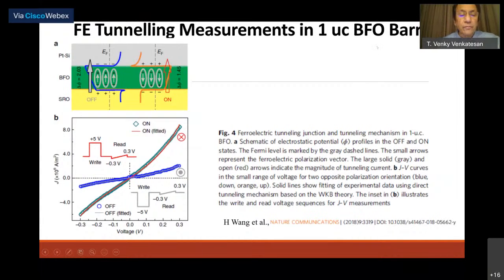We've also demonstrated with bismuth ferrite (BFO), a 1 unit cell ferroelectric layer, and here is an on-off ratio, which is very finite, telling you that a 1 unit cell ferroelectric behaves like a ferroelectric. Prior to these data, there was a belief among theorists that it takes a minimum of 3 unit cells of ferroelectric to be a ferroelectric. But it turns out that one is just good enough, okay?